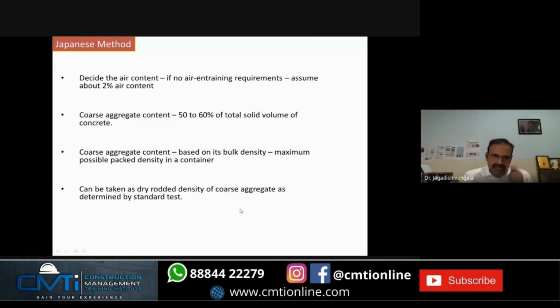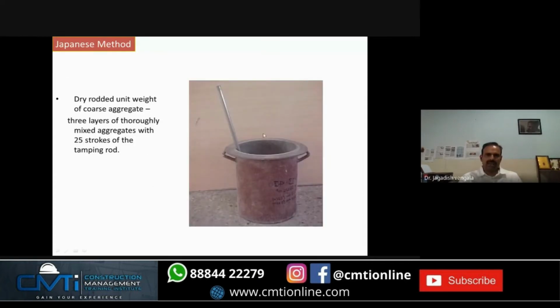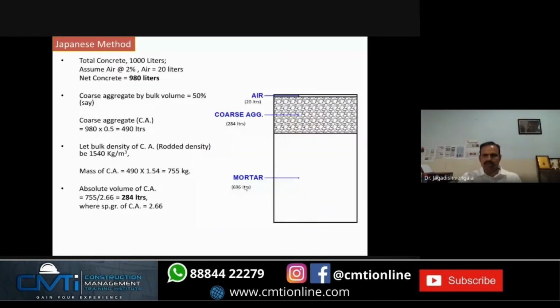So what you do in this method, you decide the air content. It depends, like 2%, 1%. And then you fix the coarse aggregate at 50 to 60%. You measure the coarse aggregate bulk density, the dry rodded density. This is how we measure the dry rodded density of the coarse aggregate: place it in 3 layers, 25 strokes each layer. That is the dry rodded packed density of the coarse aggregate that you take for the calculations.